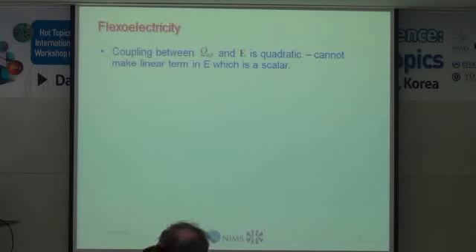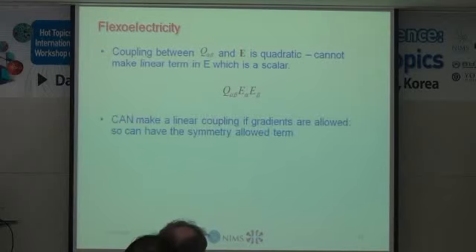Now, it's clear, for example, that if you want to make a scalar to put into the free energy, then you cannot have a linear coupling to E of the order parameter tensor, because you cannot make a scalar that way. So usually we have this quadratic term. On the other hand, if you allow gradients, then you can make a scalar. So repeated indices means summation, the usual Einstein convention.